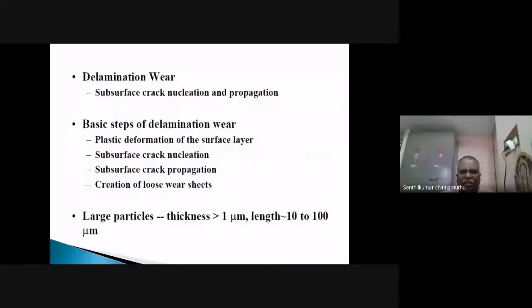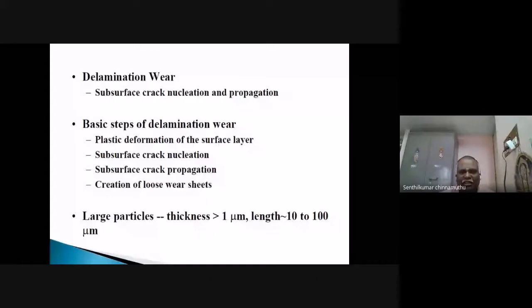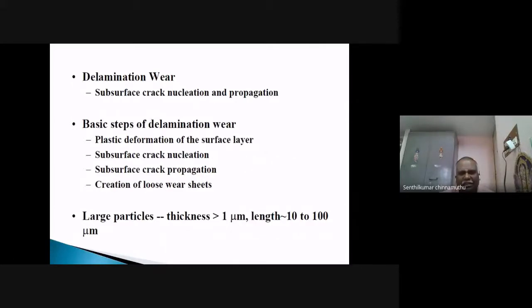Delamination wear occurs due to subsurface nucleation and propagation. Nucleation means the crack is formed, and it is propagated and enlarged. The basic steps of delamination wear: plastic deformation of the surface layer first occurs. Due to plastic deformation of the surface layer, a crack is nucleated in the subsurface, that is, below the surface. That crack is propagated, and loose wear sheets are created, with large particles of greater than 1 micron thickness and a length of 10 to 100 microns.